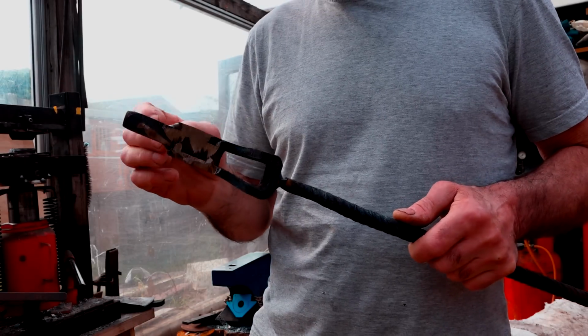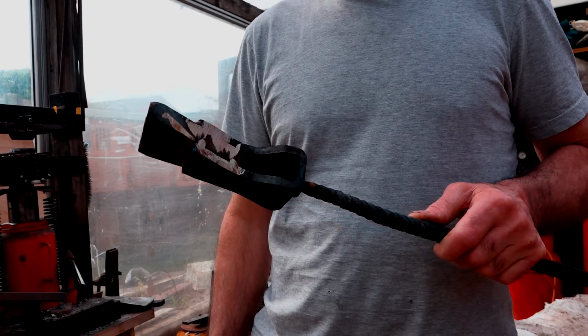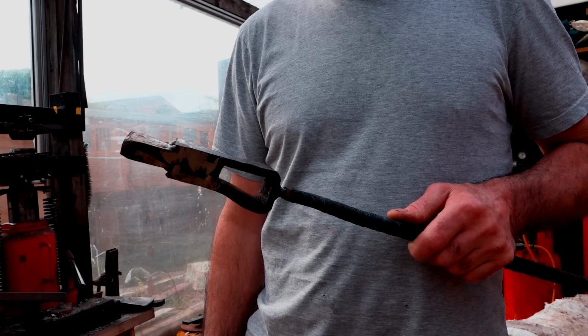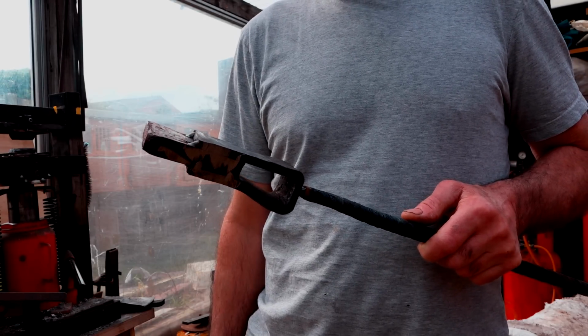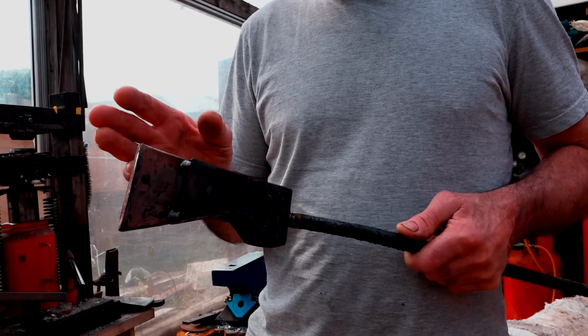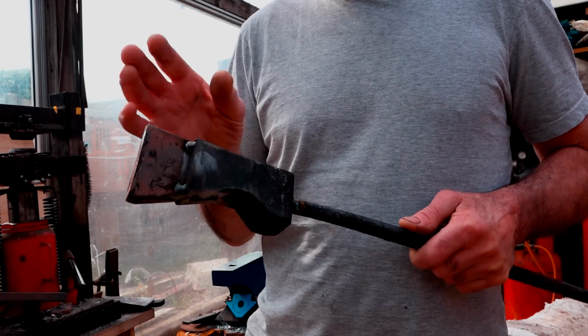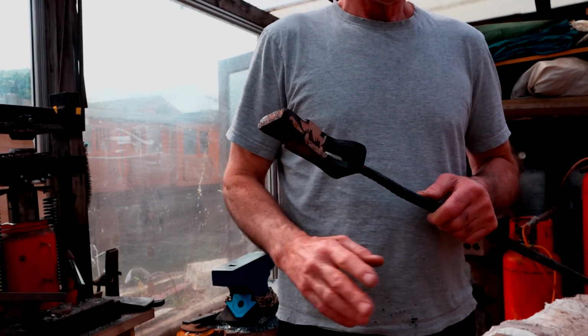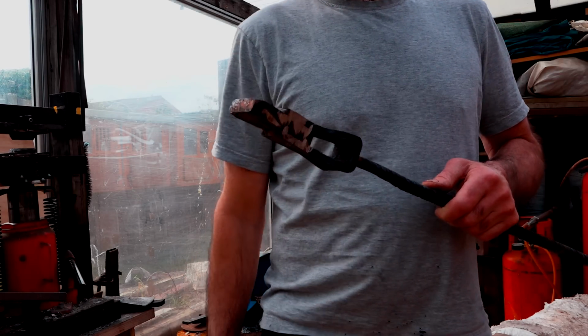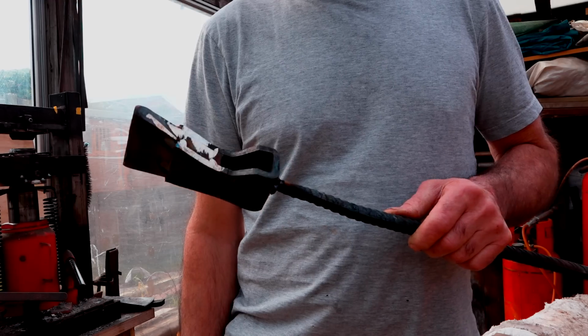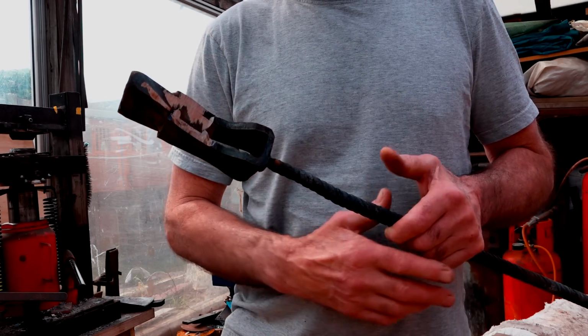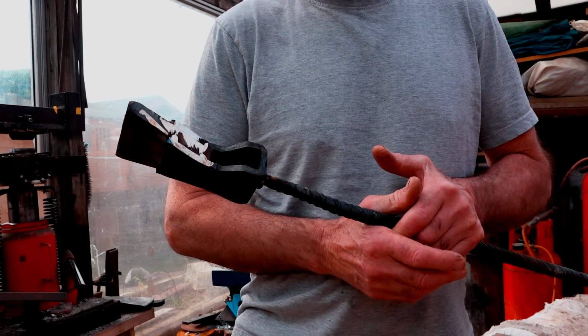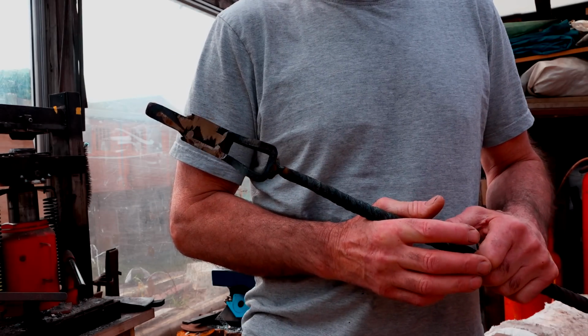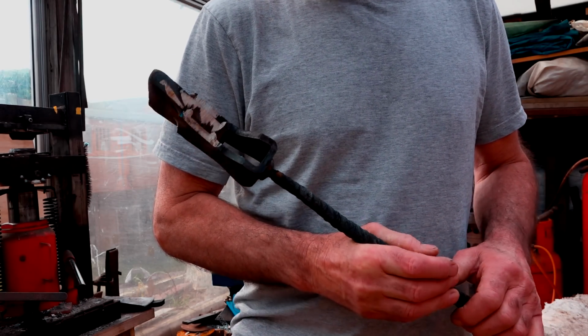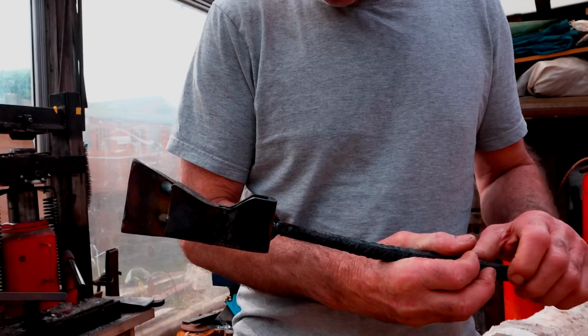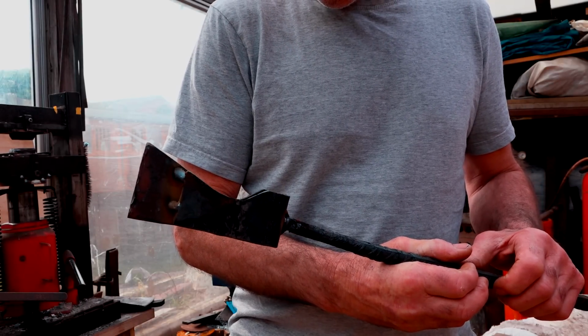Everything is visible later on when you come to work the steel, and a poor weld can also fall apart during heat treating, especially during quenching. The blades can sometimes delaminate and crack and split, which, you do a lot of work to get to the quenching stage, and to miss out a few little steps is heartbreaking when the steel cracks, because you've basically got a worthless piece of whatever you've made. So yeah, clean the steel, grind it clean.